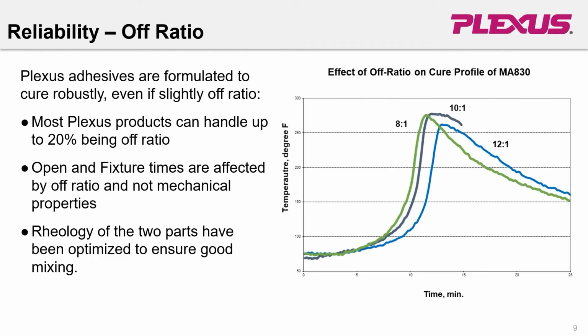The big thing is reliability in the industry. So most Plexus products can handle off-ratio cure up to plus or minus 20%. In fact, some customers in the winter will purposely go off ratio and have more activator, so it goes faster to combat the colder temperatures. And in the summer, go a little slower, maybe 12 to 1, so that when it's hotter, it keeps the reactivity very similar.